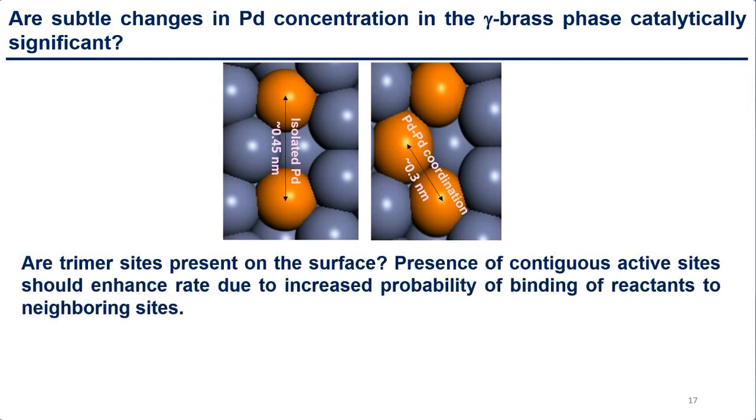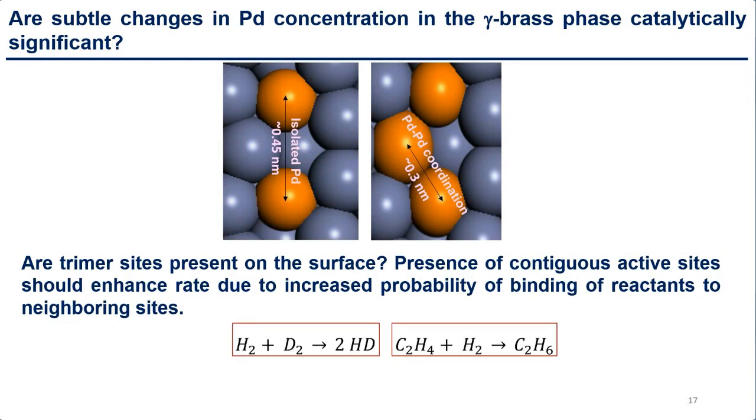And so we're going to explore that basically through 3 sets of reactions. The first 2, which really focus on activity, are H2/D2 exchange on these monomers and these trimers, and then the hydrogenation of ethylene on these monomers and trimers. And to probe differences in selectivity between isolated and trimer sites, we'll use the semihydrogenation of acetylene in order to probe the influence of nuclearity on selectivity.